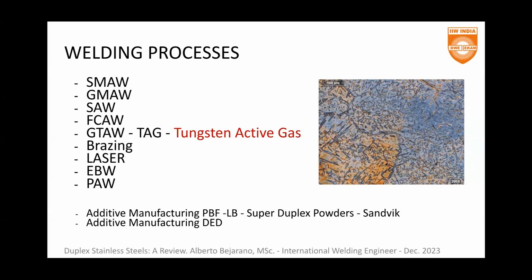And very important, when we talk about GTAW, gas tungsten arc welding, in the case of duplex stainless steel, we talk about TAG, tungsten active gas, because by the addition of small quantities of nitrogen, we are able to obtain a different microstructure. Because remember that nitrogen is a very strong austenite stabilizer. Okay, it's very important. It's an active gas for us.